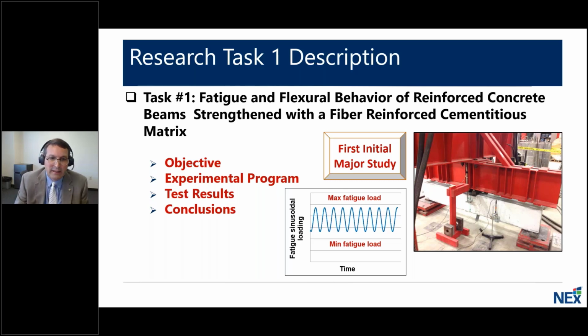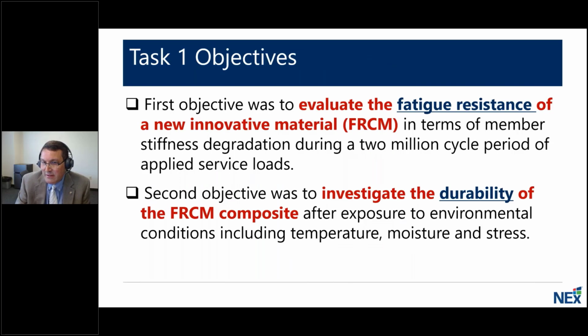And when this was done, it again was the first study that I was aware of looking at this combination. That combination includes evaluating the fatigue resistance of this new FRCM system, subjecting the test specimens up to 2 million fatigue cycles, and secondly, investigating the durability of the FRCM composite subjected to environmental conditions. And for those of you that work in durability of composites, typically the big 3 are temperature, moisture, and stress